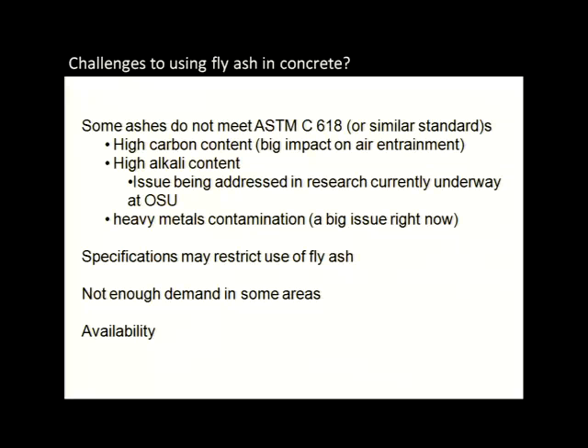Another thing is that certain specifications, like the ACI Structural Building Code, limit the amount of fly ash that you can use. They do this because of finishing issues and the concern with salt scaling. But there are certainly a lot of applications where we can use higher volumes of fly ash, and this is something that we're trying to change through ACI and through ASTM.